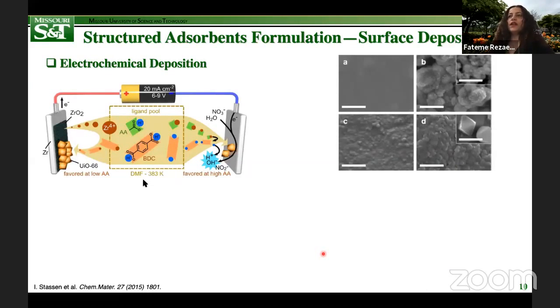Film deposition is an enabling technology for integration of novel functional materials into real world practical applications. In a recent study, through a novel approach, an electrochemical film deposition of UiO-66 MOF was reported using zirconium foil as the only metal source, as you can see from this schematic image. So here, the film formation mechanisms at the cathode and anode resulted in a significantly different coating adhesion strength, mainly because of the formation of an oxide, zirconium oxide, this green sheet on the anode, which served as a bridging layer at the surface.